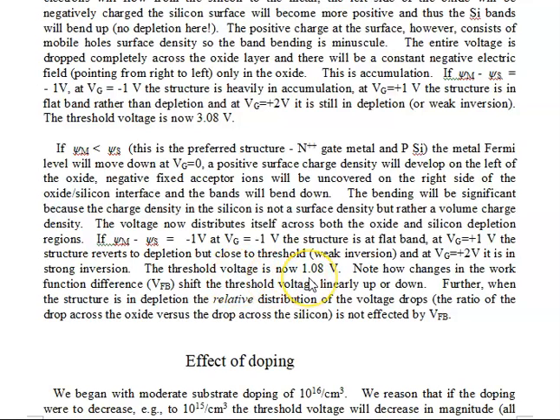Okay, so again, 1.1 volt or so positive for threshold is not too high, not too low. It's kind of in the middle. We're going to examine threshold voltage of just over a volt or so is not too high, not too low. It's kind of in the middle. And the important thing is that the work function difference, flat band voltage, shifts the threshold up or down. And when the structure is in depletion, the relative distribution of the voltage drops across the oxide and the silicon is not, I probably should put that in bold, is not affected by the flat band voltage. It is only affected by the gate oxide thickness and the doping of the silicon.